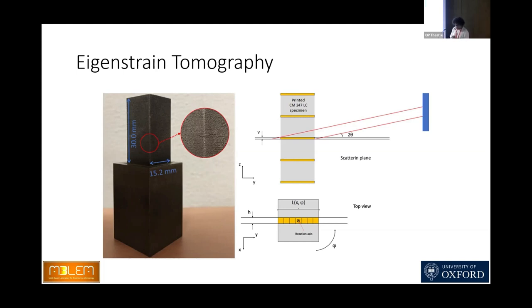Tomography measurements are performed using high energy monochromatic 2D diffraction setups, ID15 in ESRF, from five planes that are illustrated as yellow strips. The beam is collimated to spot size of 100 times 100 micron. The thickness of each yellow strip is around 100 micron.